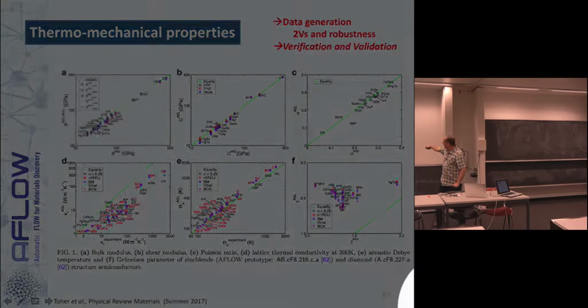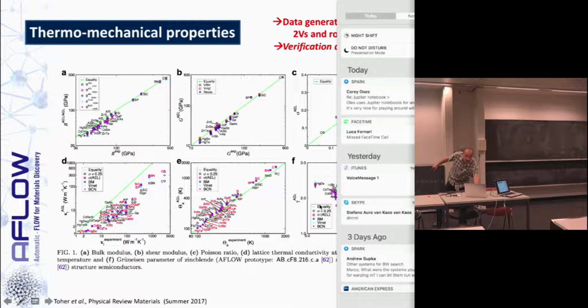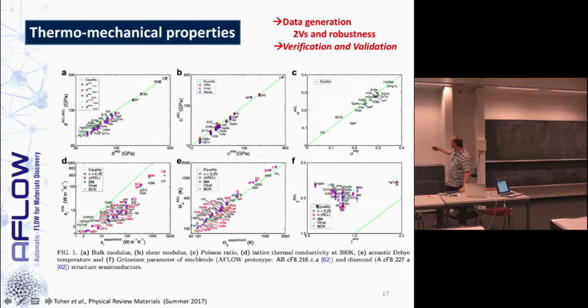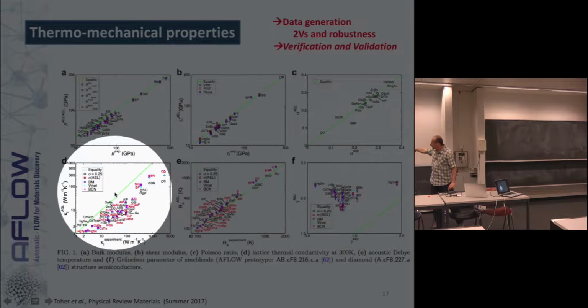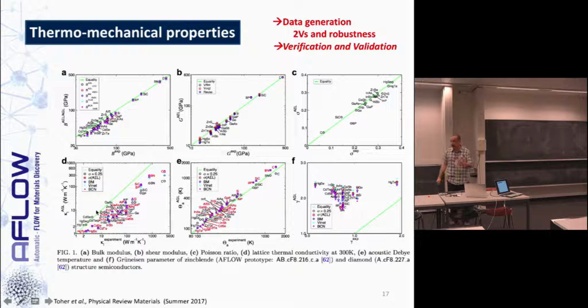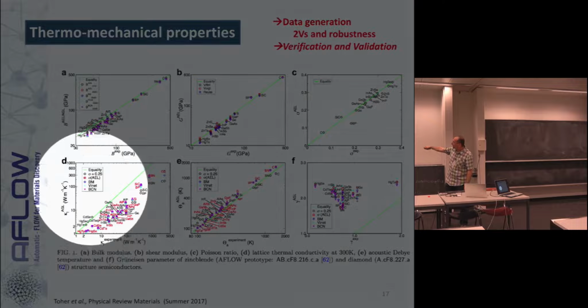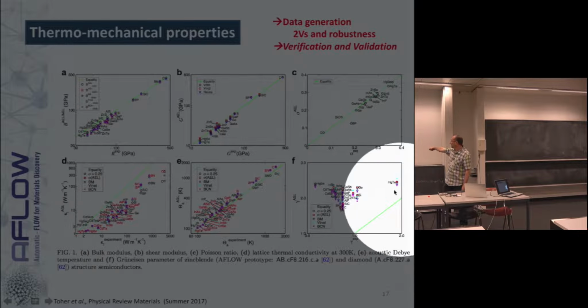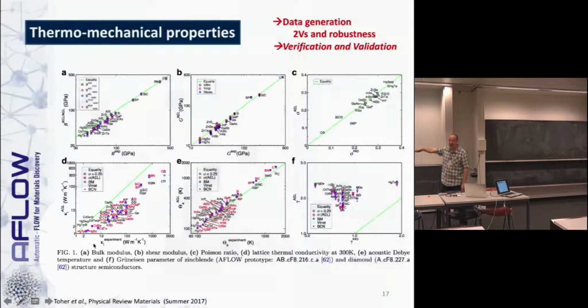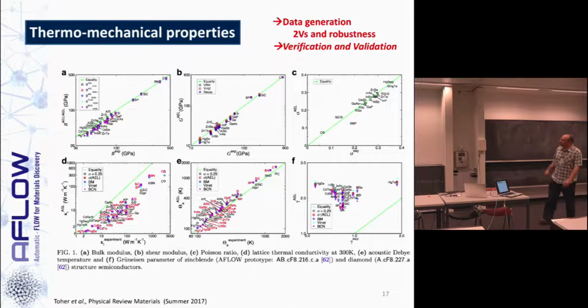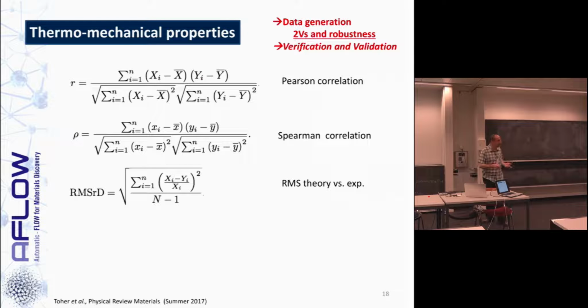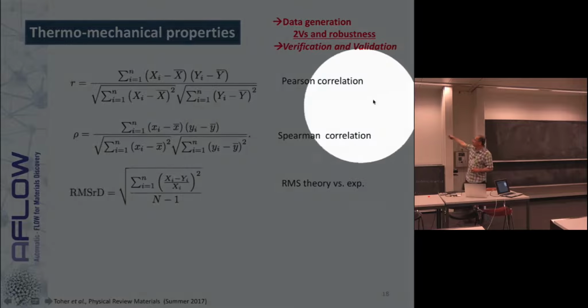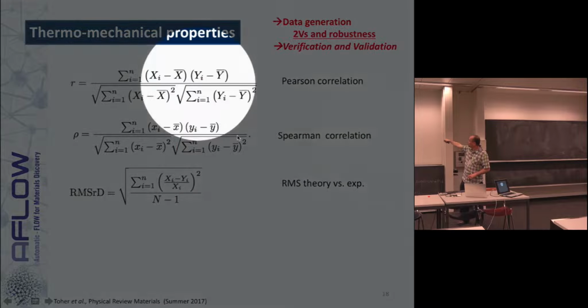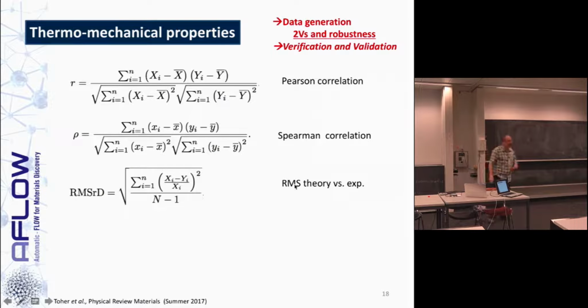On the other hand, the Grüneisen parameter is awful. It doesn't capture the experimental data at all. The thermal conductivity does a little bit better. This is a Debye-Callaway model for the thermal conductivity, but this is fictitious because the Grüneisen parameter is an input for this. So this is just a coincidence, happening through, I don't know, cancellation of errors or something. This was interesting, and in order to give a quantitative sense to those analyses, we computed the correlation in terms of the Pearson, the standard correlation, or the Spearman correlation, or just the deviation from the experimental data.